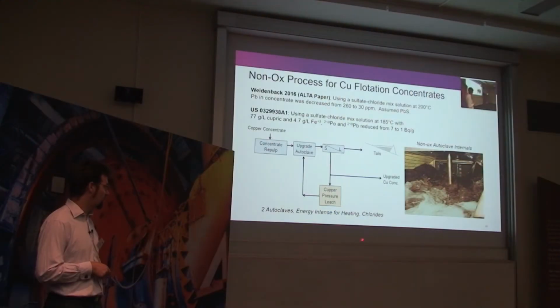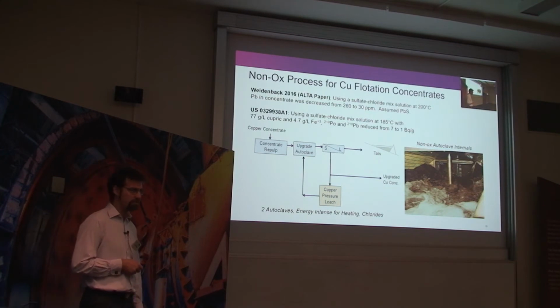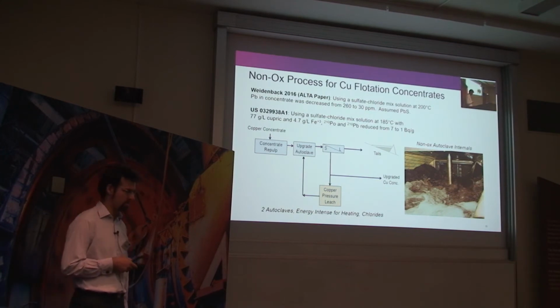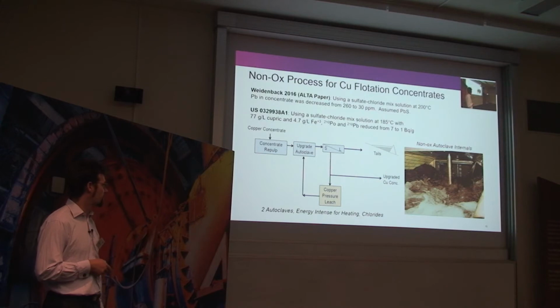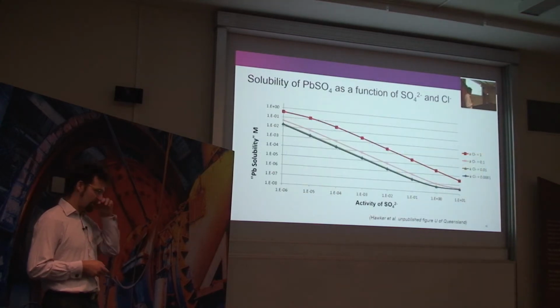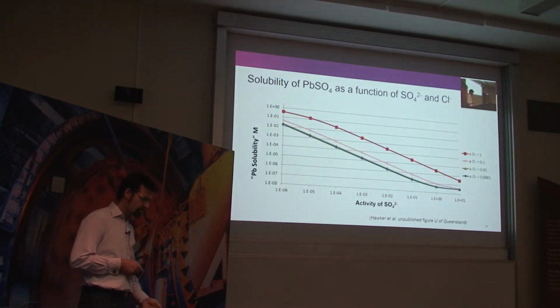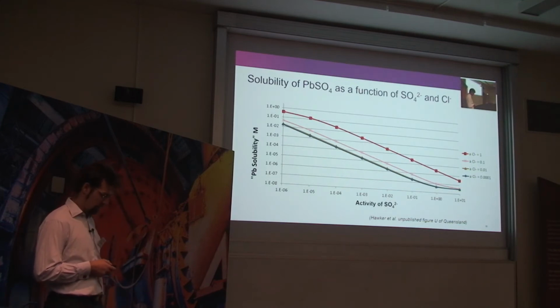There's actually quite a bit of energy required in this process for heating that type of slurry up to 200 degrees Celsius. And also chlorides are required, which can make for more expensive materials of construction, for example. So why are the chlorides required? I'll explain that with this chemical thermodynamic diagram.